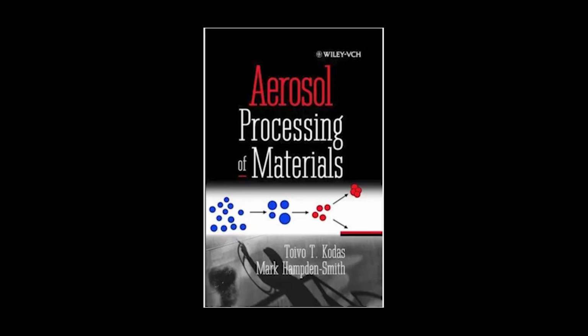Let's dive into the common types of thermally induced reactions, starting with inorganic compounds. A classic example is the decomposition of metal nitrates. They're widely used because they generally decompose pretty cleanly to the metal oxide you want, releasing harmless gases like nitrogen and oxygen. But the decomposition temperatures are all over the place. Wildly different. Aluminum nitrate decomposes around 150 Celsius, while strontium nitrate needs 550 Celsius. That huge range means the reactor geometry and heating profile has to be custom designed for every material. You can't just swap them out.